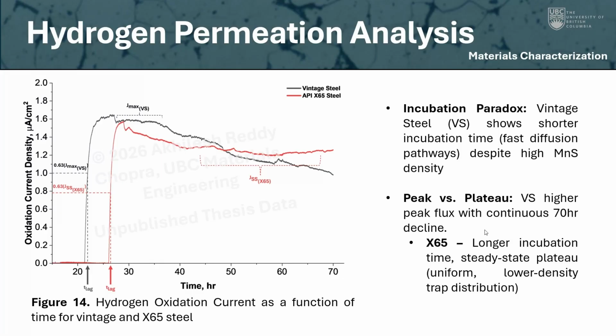So from the vintage steel, we can surprisingly see a shorter incubation time. That's the black line. When I say incubation time, that's where we essentially have no current and then a sudden spike in current. So that's when the first hydrogen exits the steel. And so that has a surprisingly lower incubation time compared to the X65 steel.